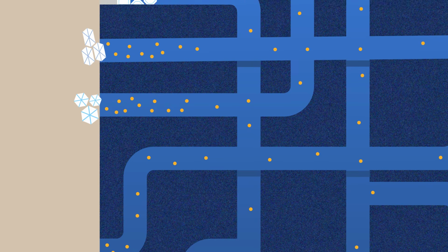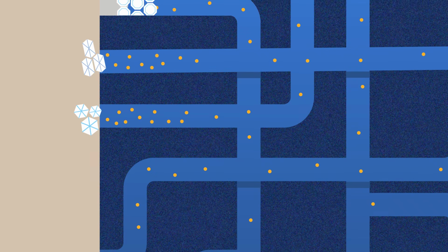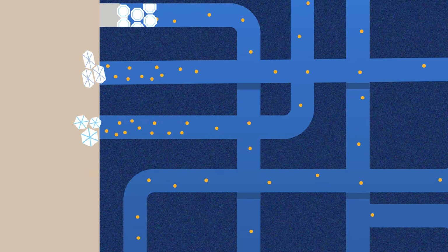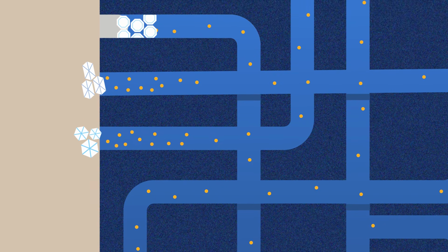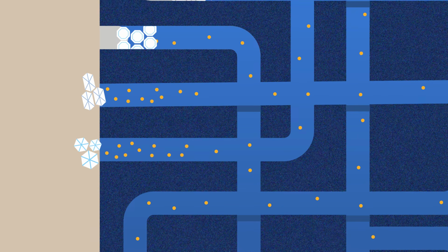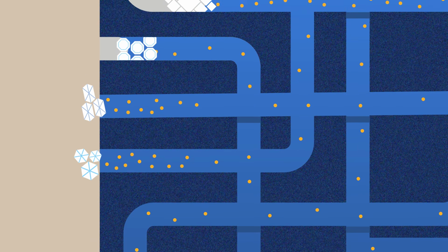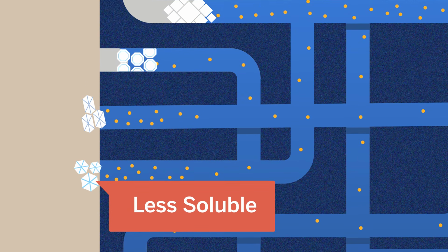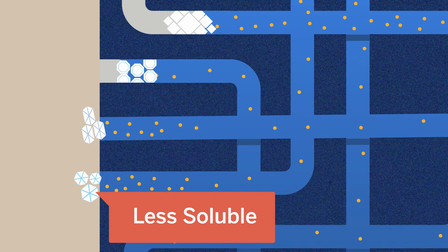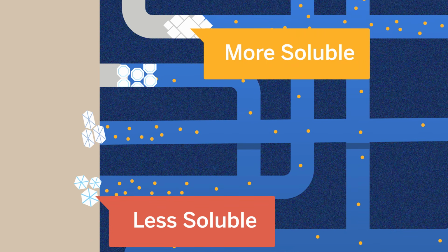Another consequence of dealing with soluble salts, and in particular mixtures thereof, is that they undergo various degrees of separation over the height of the element. Less soluble salts precipitate lower than more soluble ones.